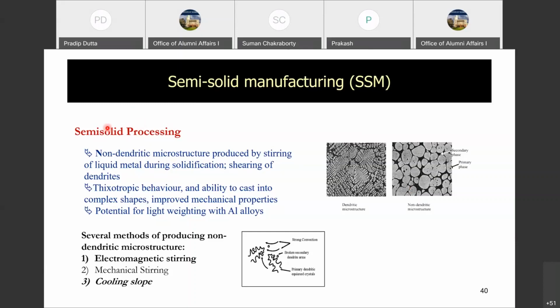Okay, this was originally invented at MIT quite accidentally. A non-dendritic microstructure was produced by stirring of liquid metal during solidification, and it was identified that because of the dendrite shearing, the dendrites would break away from the roots, and then finally when it is solidified, it would not solidify in the form of this dendritic network, but as a non-dendritic microstructure, where we have two phases. One is the primary phase and the other is the secondary phase, which is the near eutectic, the eutectic phase.